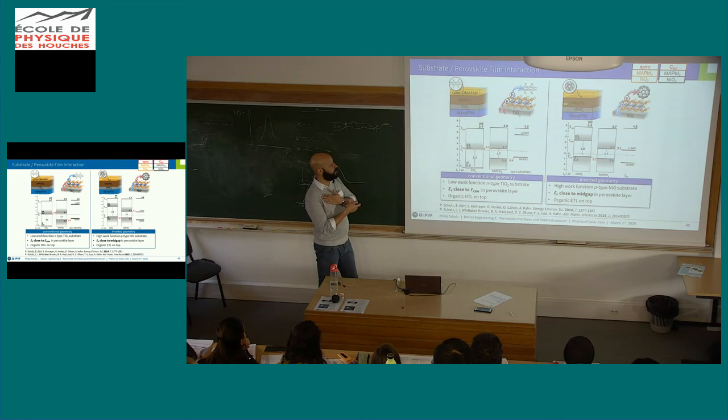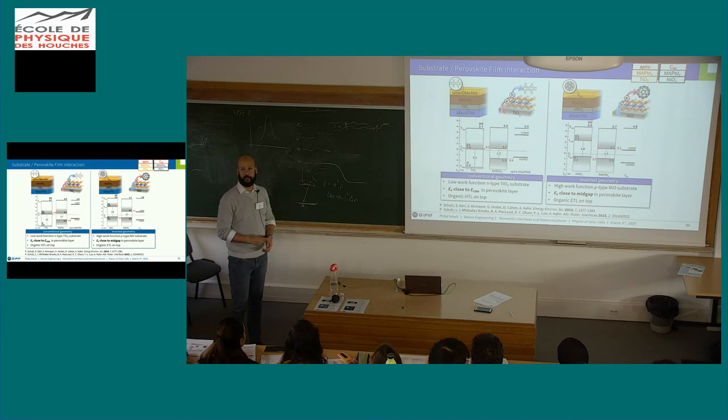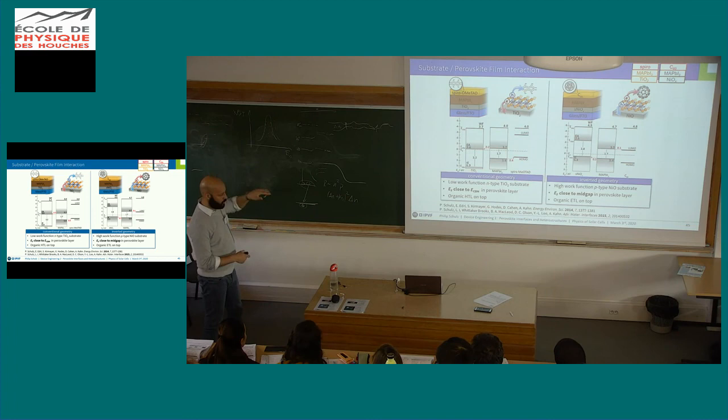And if you make these estimated band diagrams, you run in both cases into scenarios where you do not see the buildup of a significant barrier that would impede extraction and hurt the functionality of your device. We're not talking about optimization of fill factors, which rely rather on small minutiae of edge states and tail states at these interfaces, and band bending due to different doping profiles and so on. But this ensured that functionality is possible in both configurations.